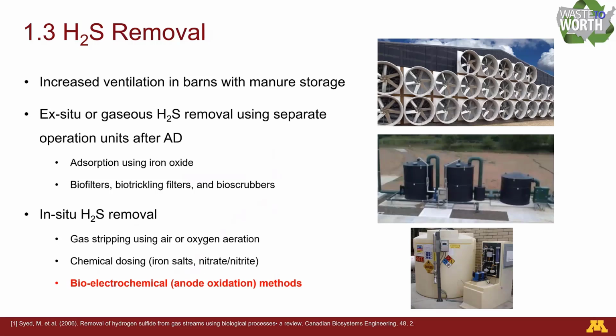So currently, the easiest way to reduce hydrogen sulfide is increasing ventilation in the manure barns just to disperse the hydrogen sulfide in the air. For the anaerobic digestion system, usually gaseous hydrogen sulfide removal is widely used, including adsorption using iron-based adsorbents or biofilters. Some in-situ hydrogen sulfide removal methods have also been developed, including microaeration and chemical dosing, but usually they require separate units outside the digester, which may increase the capital costs and the operational costs. So that brings us to our proposed bio-electrochemical or anodic oxidation method.